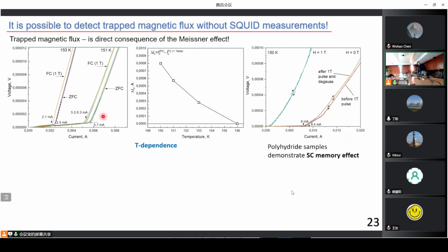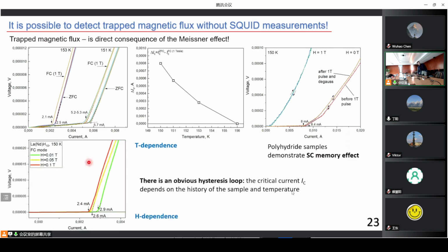We tried not applying any field, and we were able to repeat and confirm that it's a repeatable type of measurement. The same critical currents were obtained for many cycles of cooling and heating without magnetic field. And it definitely depends on applied magnetic fields in the history of the sample, I mean, in the past of the sample. When we apply a small magnetic field, the memory is very weak. But when we apply a higher magnetic field, the memory becomes stronger and stronger. So it depends on the history, on the past of the sample.